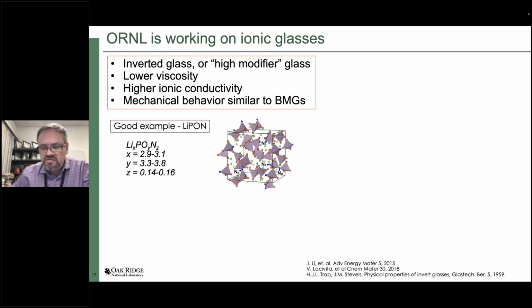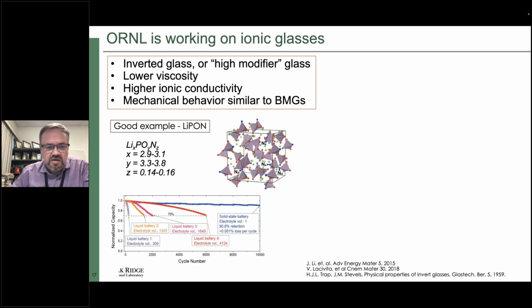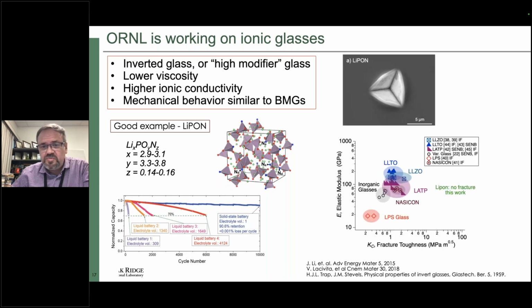And a good example is lithium phosphorus oxynitride, which was developed at Oak Ridge National Lab. We call it LiPON for short. And again, you can see these phosphate tetrahedra. Some are connected through a bridging nitrogen, some are floating in this, if you will, soup of lithium and free to move in shear. And LiPON has been demonstrated to cycle extremely well in solid state thin-film batteries, tens of thousands of cycles, with minimum capacity loss. But more importantly, it has kind of remarkable mechanical behavior.